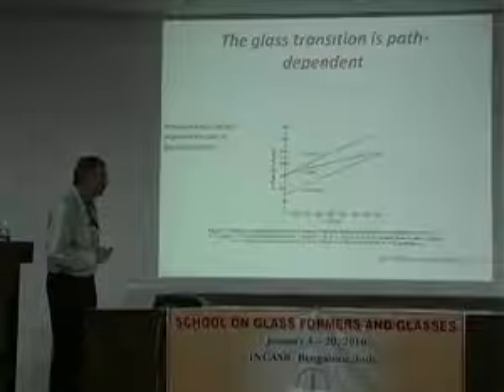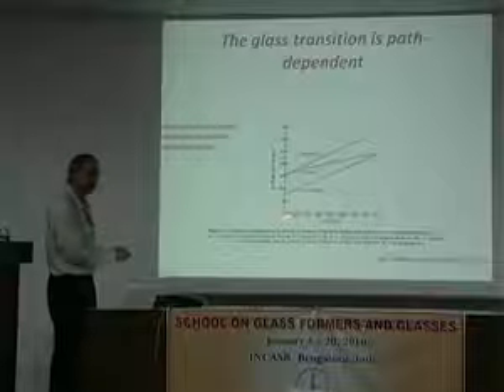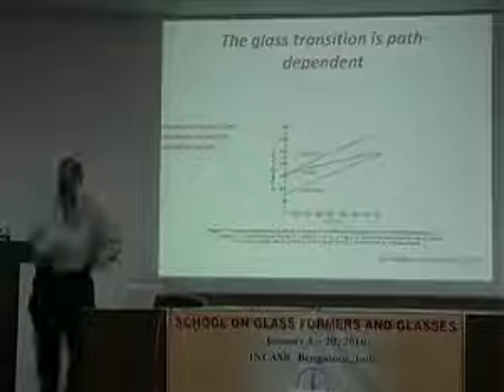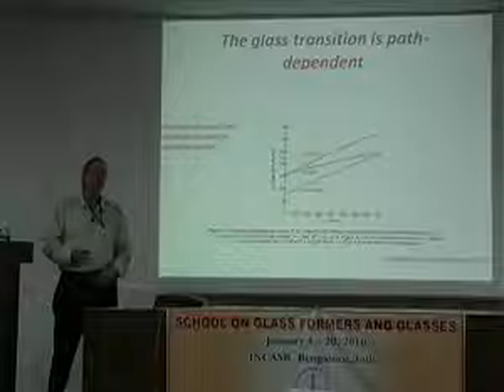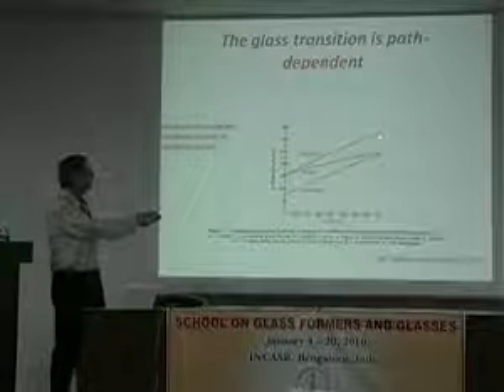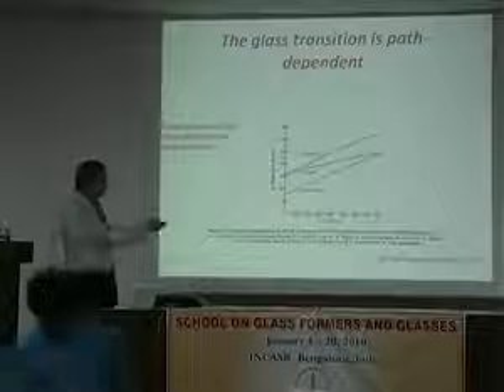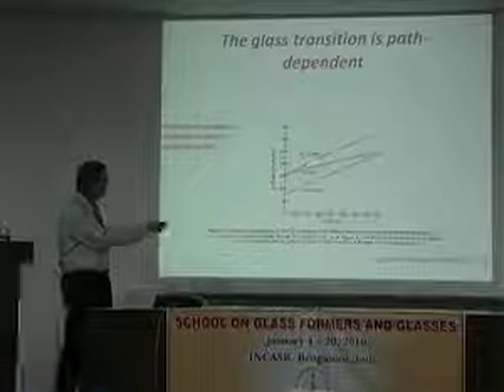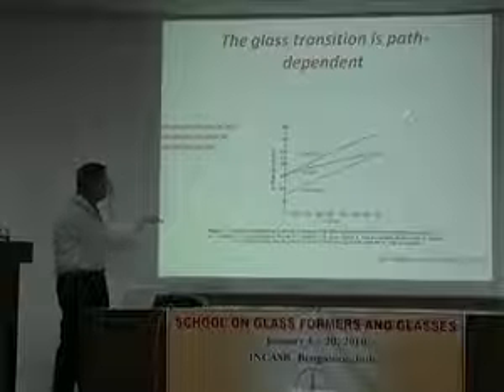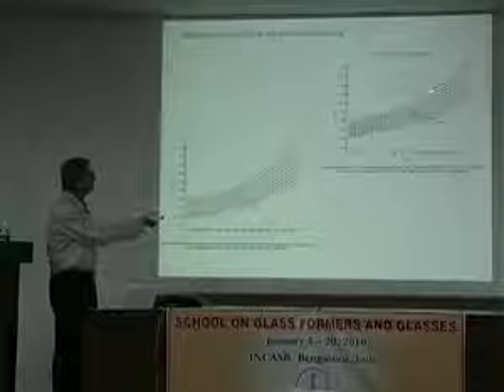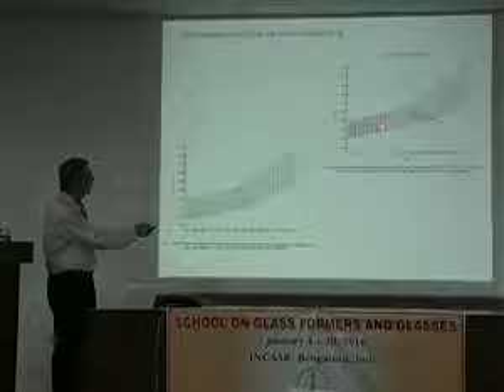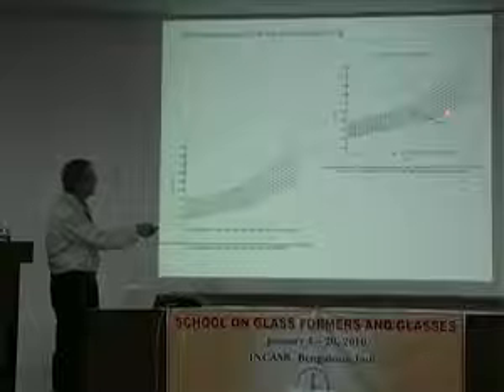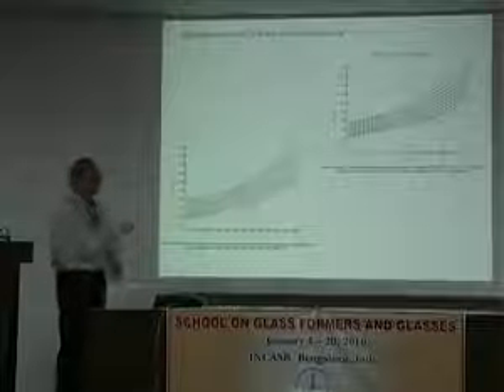This is Tg here, and this is pressure here. Yeah, Tg versus pressure. Okay, this is actually the constant formation pressure glass, or variable pressure formation glass, or what they did is they formed the glass here. The top curve is this type of curve, and the bottom curve is this type of curve where they formed the glass and then depressurized it. Okay, so in one case, the middle curve is this kind of surface. Okay, so just as the way you construct the two surfaces.